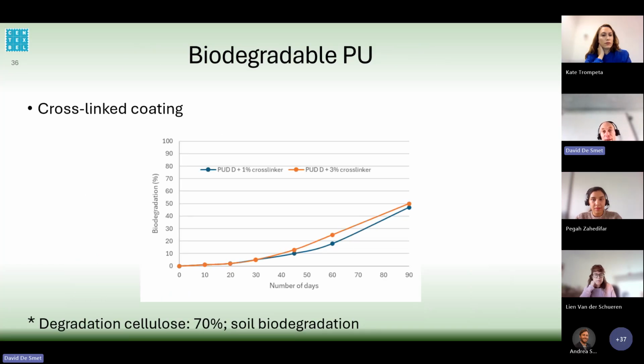Another way that we have looked at, and it's also a possibility which is going to be explored in the SUBBIMATT project, is to use a biodegradable polyurethane. Unfortunately, the biodegradable polyurethane in our case is still not completely bio-based, because the polyol is not bio-based. Here I will just focus on the results of the biodegradation process. We did an ISO test at 25 degrees, so a soil condition test, of a cross-linked PU coating. We put it in the soil, and after 3 months we had a look at the biodegradation of this PU coating. We could see that after 3 months, the coating was 50% biodegraded, which is quite a lot, because normally PU coatings are not biodegradable.